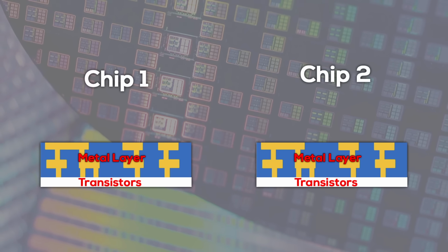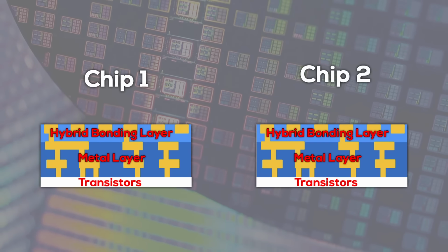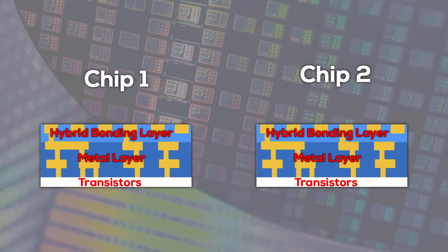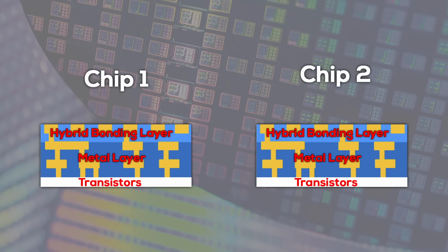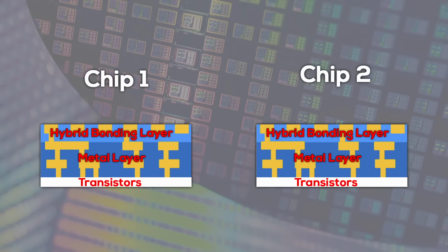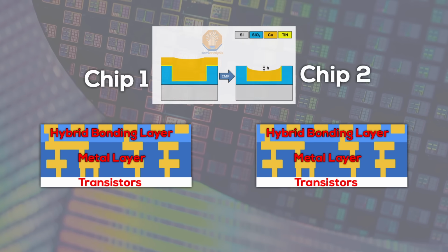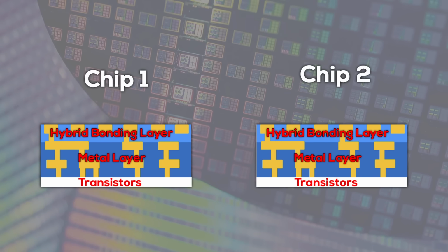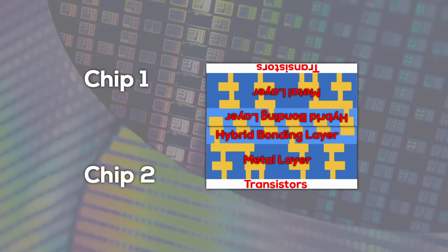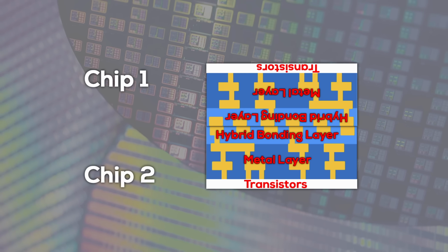In a first step, the surface of both chips, usually as part of a wafer, is treated and prepared with a dielectric material, and the matching copper interconnects are revealed. The copper is a bit recessed from the dielectric material. Now both wafers are perfectly aligned in a vacuum and pressed against each other. Because the copper in the bonding layer is recessed, the dielectric material, for example silicon dioxide, touches first.